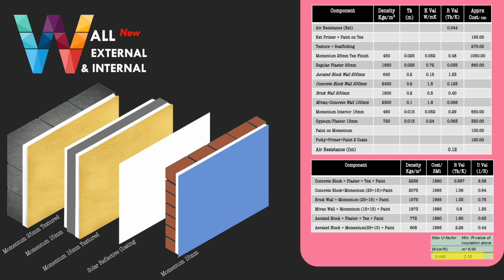Our recommended system will include aerated blocks with Momentum plaster on both sides. This system provides a system R value of 2.26 and U value of 0.44, which are both as per norms. If we consider density of all systems, our recommended system will be 75% lighter than the conventional system, reducing static load